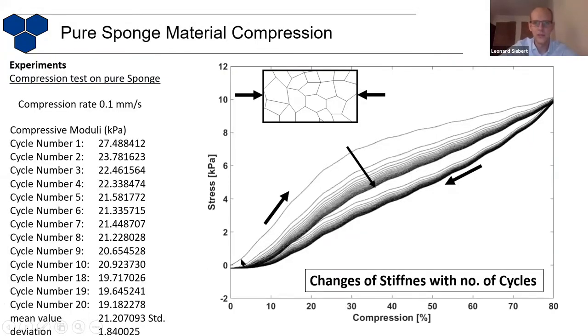This is probably the reason for the lowering of the overall modulus — the more connections break in the network, the lower the overall contribution to stiffness. But you can also see that this converges onto one value — it's not decreasing anymore after some cycles. This means the connections that were stressed and broken before are no longer contributing, but the remaining network still distributes stress quite nicely. This overall trend depends on how much you compress the material.